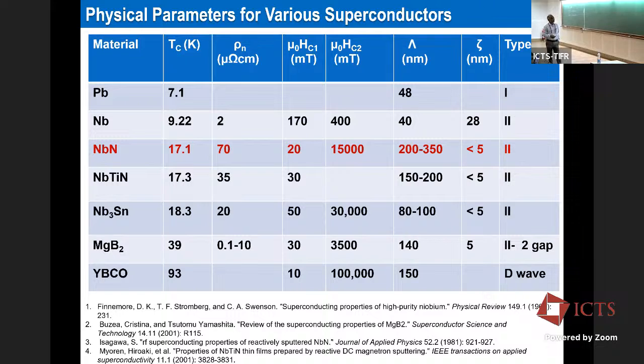If we go to NbN, which has a Tc of 17 Kelvin, yes, this makes our life a little easier to develop better cooling systems. And this rho n, the normal state resistivity, is 70 micro ohm centimeter, indicating that NbN has low granularity and the mechanical properties are very good. So we can easily develop those coil geometries. On the other hand, a challenge is there because we have some kind of granularity, which makes it challenging to make this coil geometry while doing the lithography.